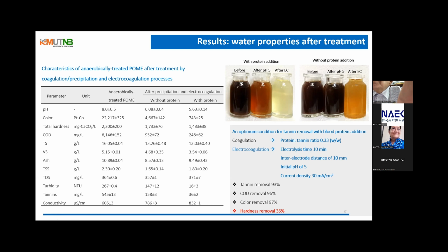And the covered lagoon effluent appeared dark brown with a color value of about 20,000 platinum cobalt unit, and tannin concentration of about 545 milligram per liter. After the treatment, the treated effluent appeared light yellow with a color value of about 700 platinum cobalt unit and tannin concentration of 36 milligram per liter. However, the total hardness is still high, and we need to manage it further.